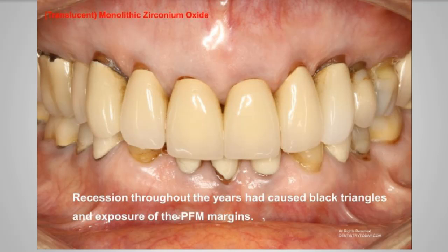Cementation failures are probably the number one cause when you look in the literature for failures 6 months, a year, 2 years, 3 years out. Cementation failures, microleakage, recurrent caries, gingival recession like you see here, black triangles, the formation of black triangles, periodontal problems. These are the number one reasons, if you lump them together, that we have to remove most of the crowns that require removal. It isn't fractures. Fractures bother us because, you know, if you have one, it's one too many. But when you really think about it and you look at all the practices collectively, situations like this far outnumber the fractures that we've had over the years, and we looked at that in the literature in part 1.